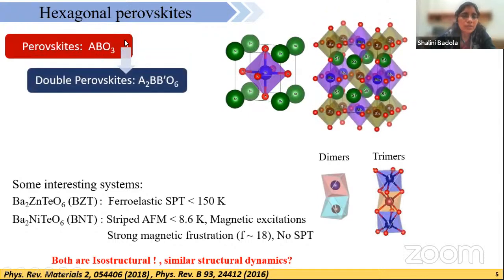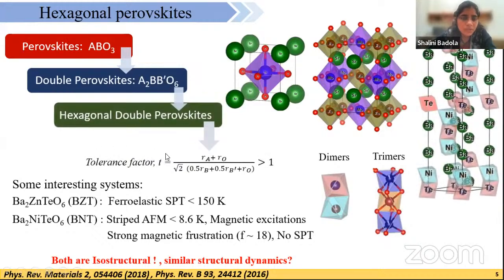These manifestations can be studied, or are generally found, in perovskite oxides with general formula ABO3, where A is usually a divalent cation and B is a transition metal ion. As we introduce an additional cation at the B site, double perovskites of the form A2BB'O6 get stabilized, which may take various structures depending upon the size of the A or B site cations and their corresponding valences. The phase stability of these materials is decided by an empirical relation given by the tolerance factor, which is ideally unity for a cubic material.